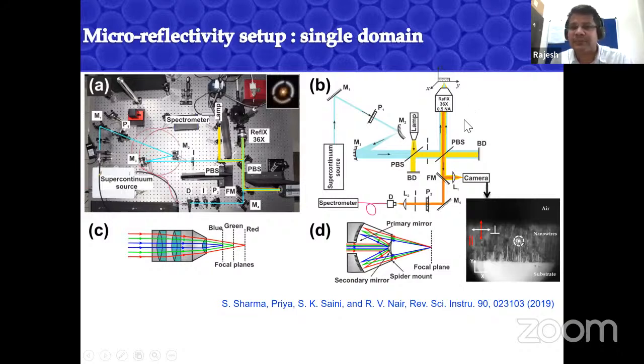The whole beauty of this system is twofold. One is that we can go down to a small area of the sample and collect the signal from there. The second is that you avoid chromatic aberration in this setup, because when you do a wavelength dependent measurement, you want all wavelengths to focus on the sample at the same position. So that is also taken care of in this setup by not using a typical lens like a glass lens we use in the laboratory. Rather, you use a curved mirror and focus the light on the sample. So we developed this setup, and let's see whether it will give 100% reflection or not.